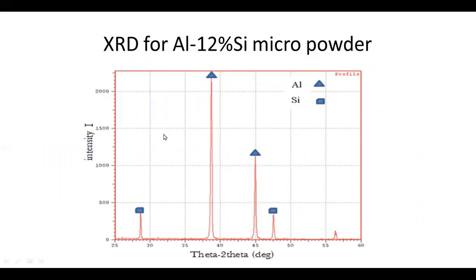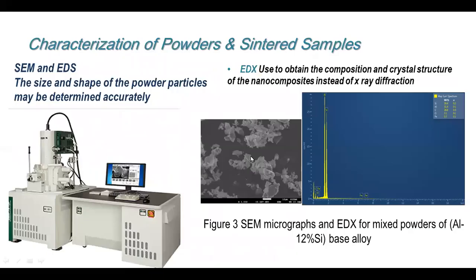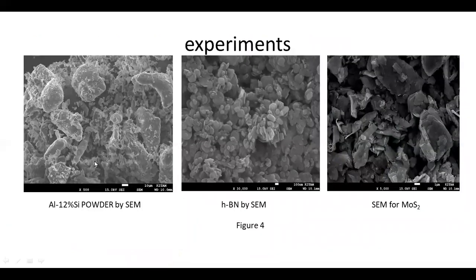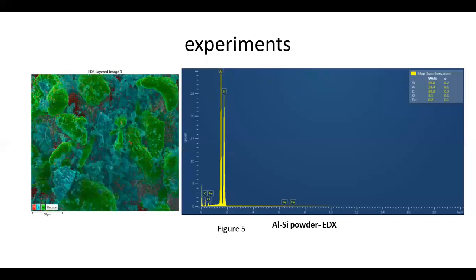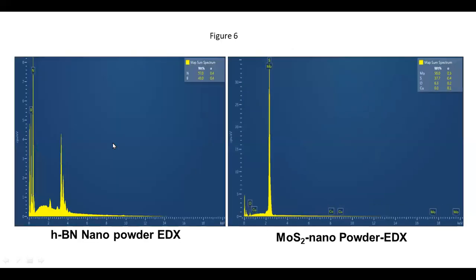Now, what we characterize by XRD for aluminum plus silicon powder. What characterization after blending with nanoparticles didn't appear for nanoparticles but appear only for micro, but we characterize by SEM and EDS to characterize what's the new alloy. Here we can see the aluminum plus 12 weight% of silicon powder from this SEM and hexagonal boron nitride by SEM and molybdenum disulfide. The aluminum silicon powder by EDX, we see the peak of aluminum and silicon and EDS for SEM image. Here what happened for hexagonal boron nitride nanopowder and molybdenum disulfide nanopowder EDX.